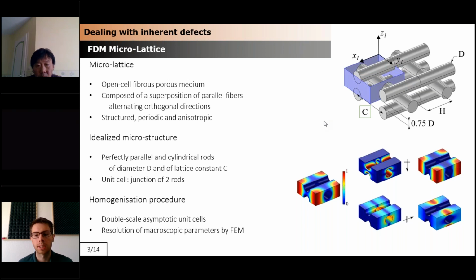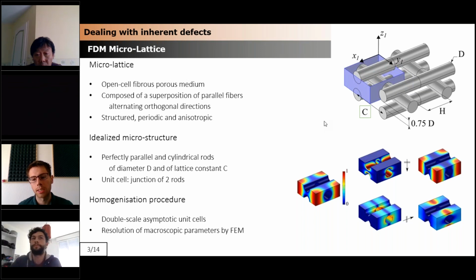What is nice with this material is that it can be simply 3D printed, and that just by changing the lattice constant, so here it's the C distance, the distance between the filaments, you can actually tune the properties of the material. So it's a simple material that we can easily 3D print, and also that we can easily simulate. It's the theory that has been presented before this morning. So you can numerically predict the intrinsic parameters of such material.